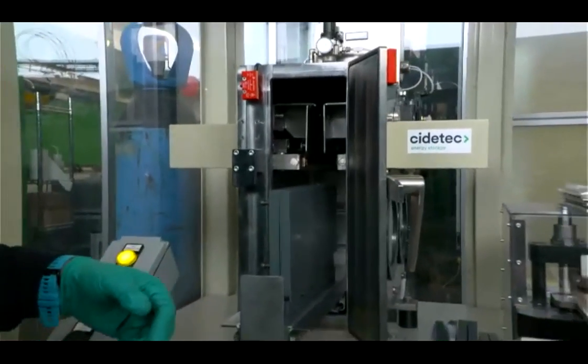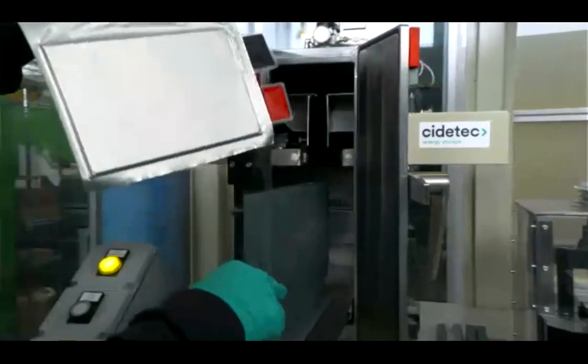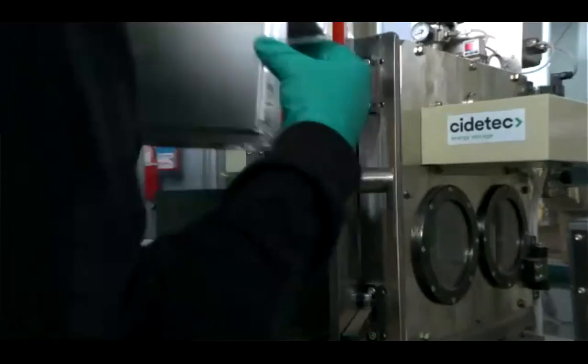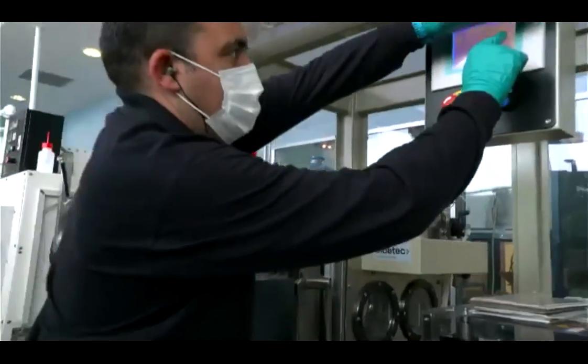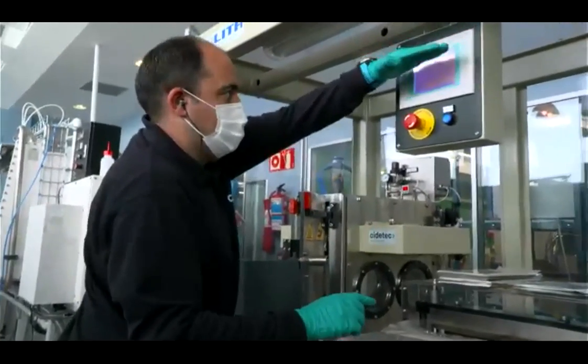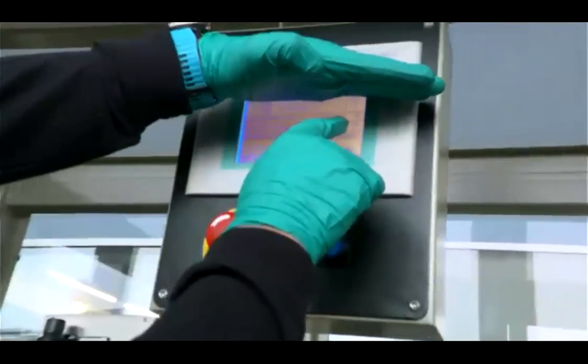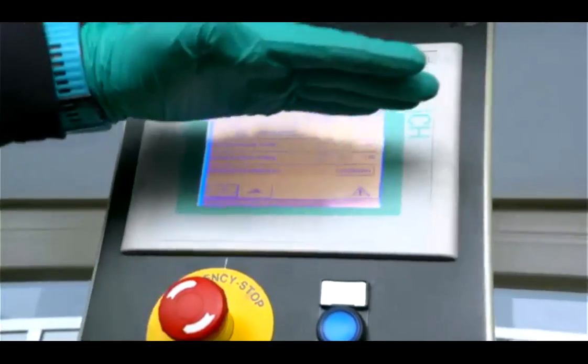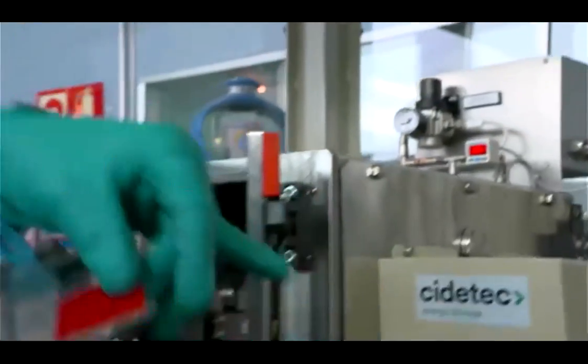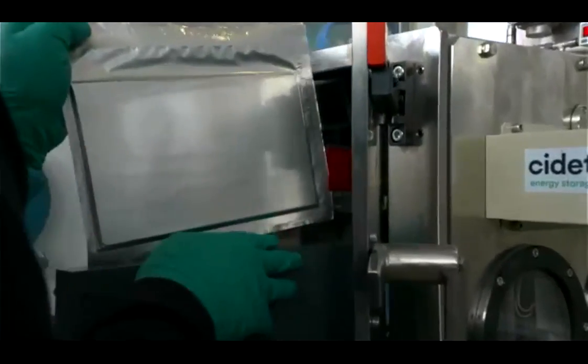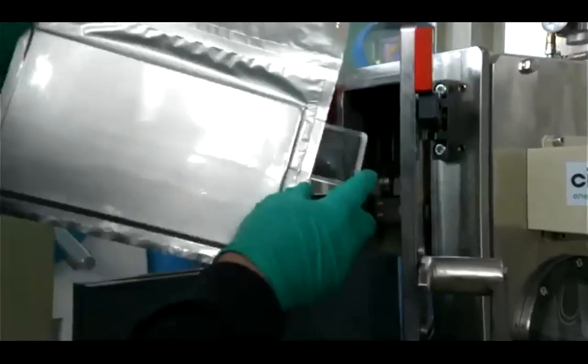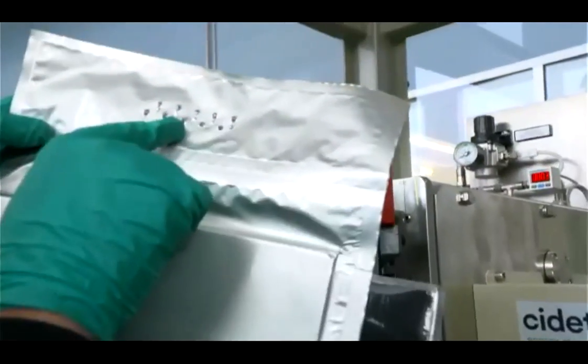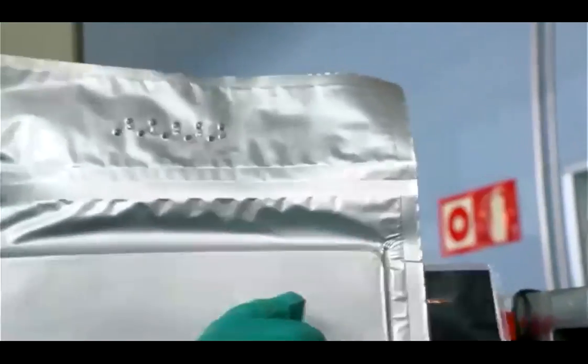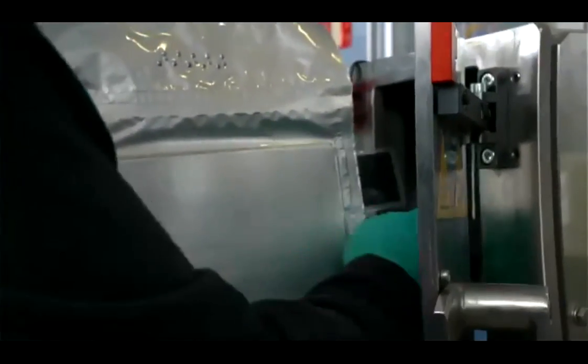And this temperature depends on this aluminum bag. In this case, our aluminum has these layers of polymer that Idoia mentioned. Depending on this, we can set the temperature, as Iker maybe can show. For the sealing bars the temperature is 105. And one thing that is very important in this part is that the cell has to be set in a very correct way, because there are these needles that make the holes in this extra part. You can see here. And here is the final seal of the cell in the sealing bars that Iker showed before.